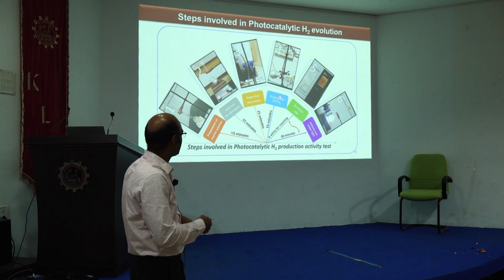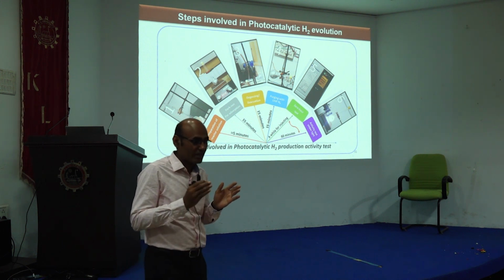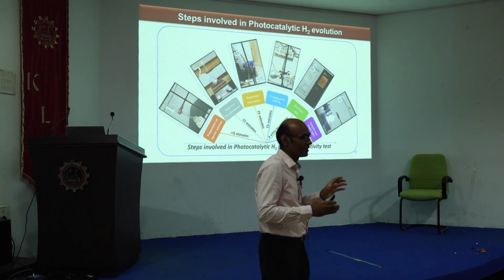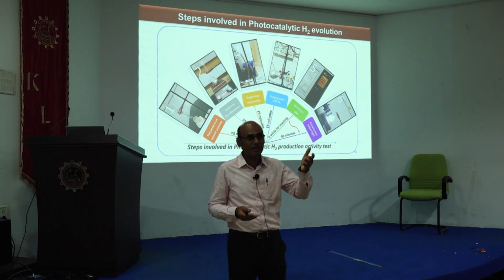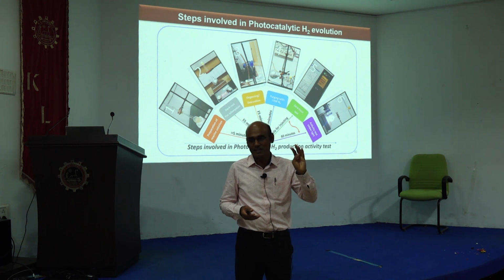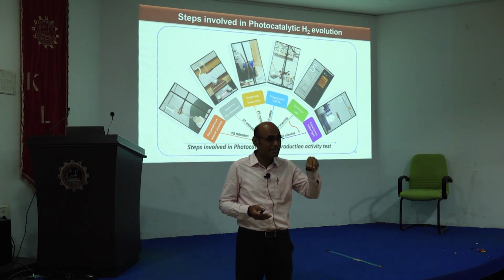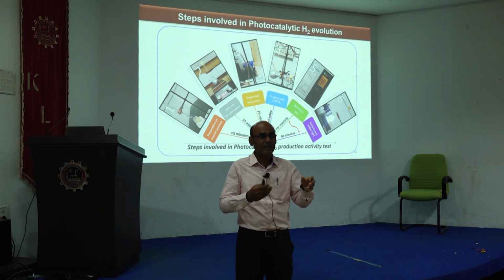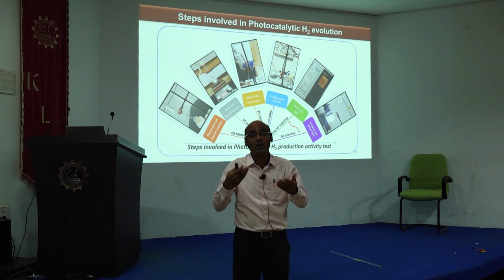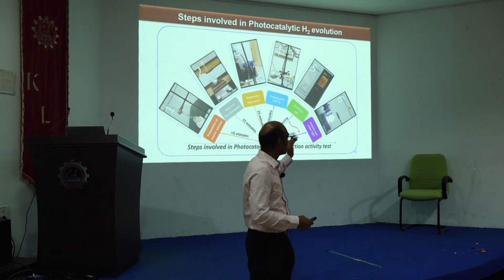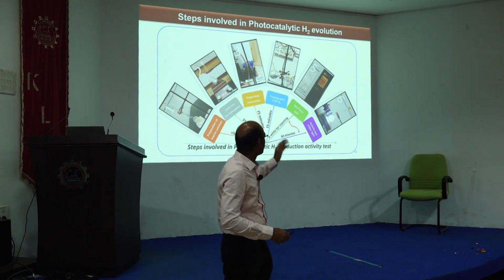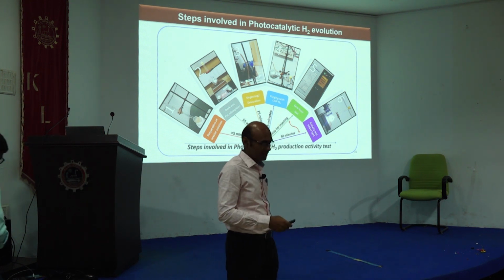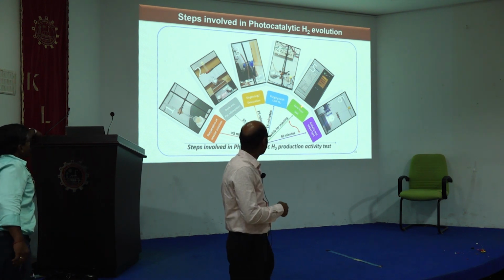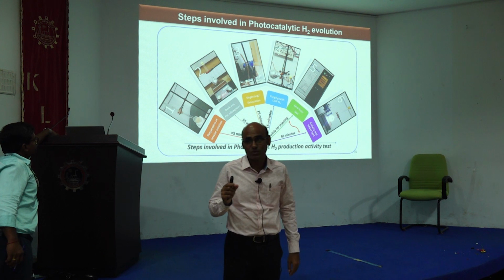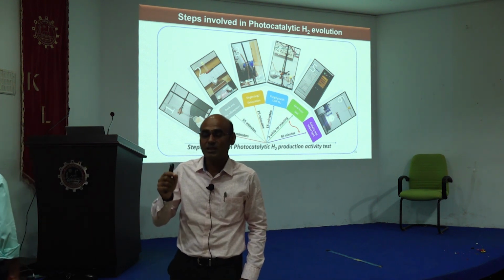After degassing and evacuation, it was purged with nitrogen, because for a hydrogen production experiment it should have an inert atmosphere. In air, we have oxygen and nitrogen. The presence of dissolved oxygen in the water can facilitate recombination: once hydrogen is generated, it recombines to give water immediately. Instead, we need to separate the hydrogen effectively, so we purge with nitrogen gas. And then we analyze the generated gas quantitatively using a gas chromatograph.